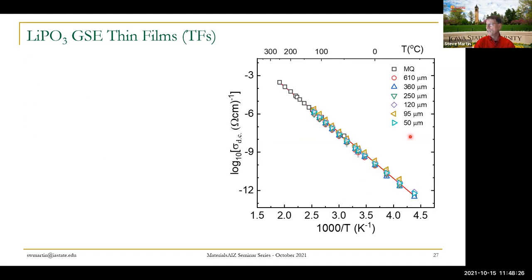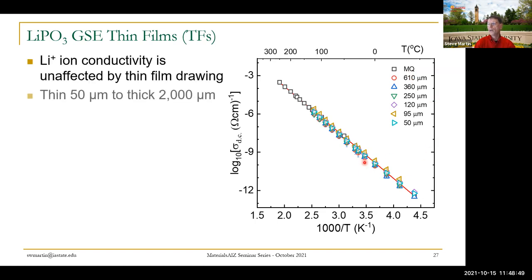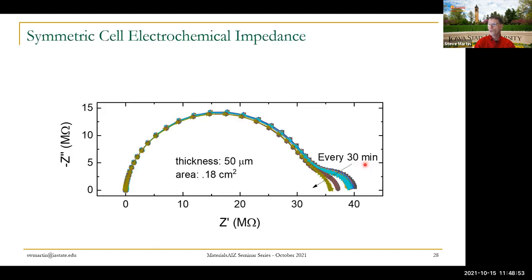The conductivity, apologize for going quickly because I want to be respectful of time. The conductivities, even from 50 microns all the way up to melt quench. Melt quench is about a 1 millimeter thick chunk of glass, made in a very different way, of course. There's a little bit of variation, but by and large, the conductivities are unchanged by the film drawing condition. Of course, what's important is electrochemical behavior.